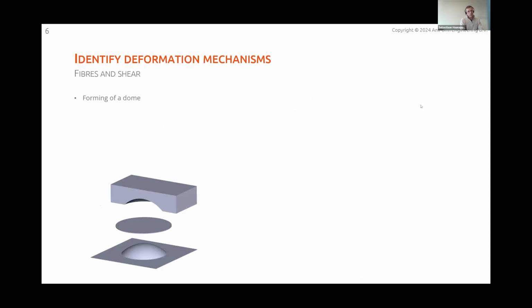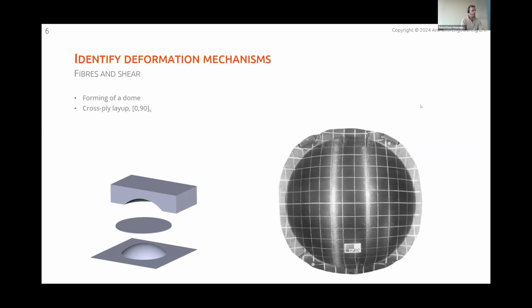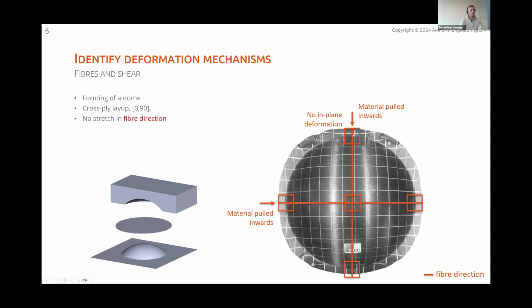And I would like to use this example for that, the forming of a dome, a circular blank, a punch, and a die on top. And we form a cross-plied unidirectional laminate like this. And if you form it, it typically looks like this. If we take a closer look, you can draw lines here in the 0 and 90 direction, and we see that the material gets pulled inwards. And we also see there, well, that is because there's no stretch in the fiber direction in those directions. We also see at those locations no in-plane deformations in those indicated spots.